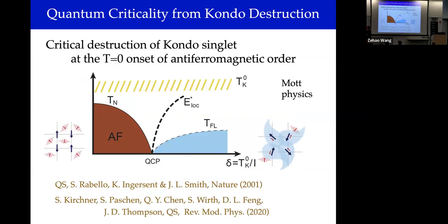But it turned out that in this class of materials, as I was showing in those colored plots of phase diagrams, there's some unusual dynamics, and we had the physical picture, but also some calculational schemes to show that you can have a type of quantum critical point that not only has the criticality associated with fluctuations of the magnetic order parameter, but also something that doesn't involve explicit breaking of symmetry, global symmetry, such as the Kondo effect in this case, which I said yesterday, that if you form Kondo singlet in the ground state, you end up with the heavy fermion state with large mass seen in specific heat, etc.